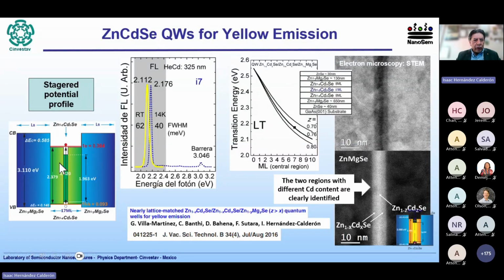And for example, here, if we introduce a layer in the middle with higher cadmium content, then we can shift the emission to the yellow. And in fact, I'm showing here an electron microscopy image of the quantum well. We have the barriers here, zinc magnesium selenide. Then we have zinc cadmium selenide with 2 different compositions in this region. At the sides, lower cadmium content, and in the center, a few monolayers with higher cadmium content. This very thin layer makes the whole change and shifts the emission from the green-blue to the yellow. And we have a very yellow emission at room temperature. This is one way to modify the potential of the quantum well. We can significantly modify the excitonic, the emission properties of the quantum well.